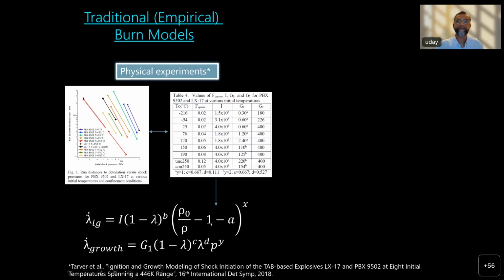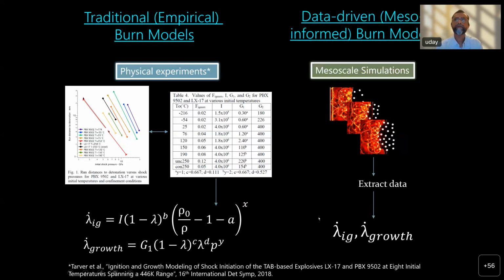where there's an ignition rate term that is dependent on the density and the compressibility of the material, and the growth rate term of hotspots that is pressure dependent. So this is a semi-empirical, phenomenological model, where all these parameters, E, X, and so on, are fit to experiments. And so there are lots of experiments conducted for each formulation, and then you get these models. Now, these are the traditional routes of empirical burn models. What we mean by data-driven models is that we are going to use simulations as opposed to physical experiments to obtain these ignition and growth rate parameters, right?